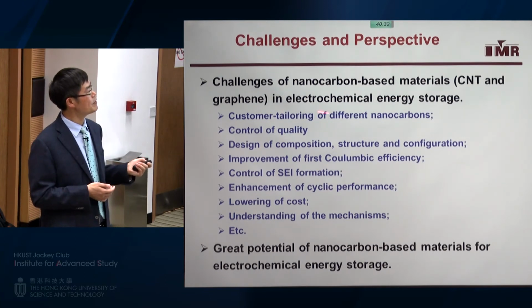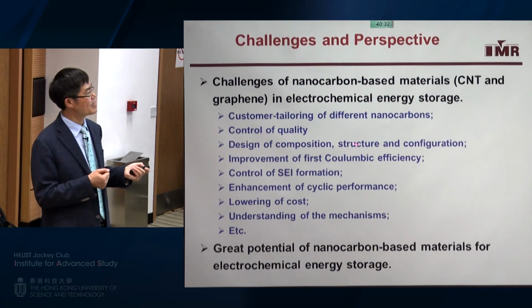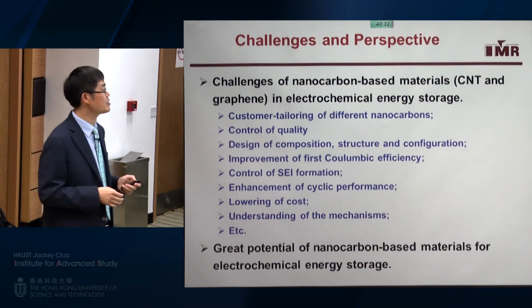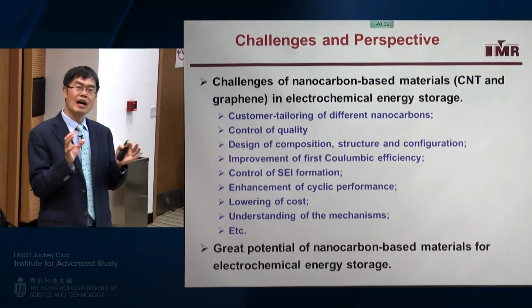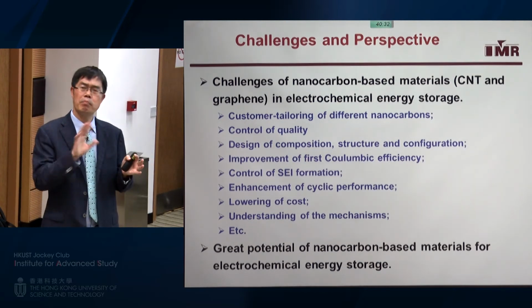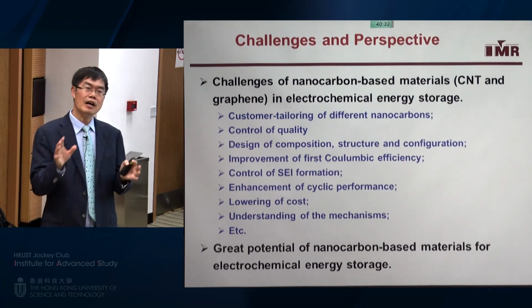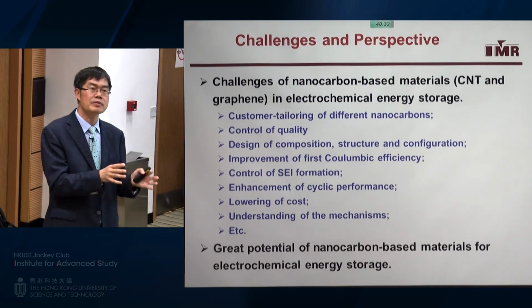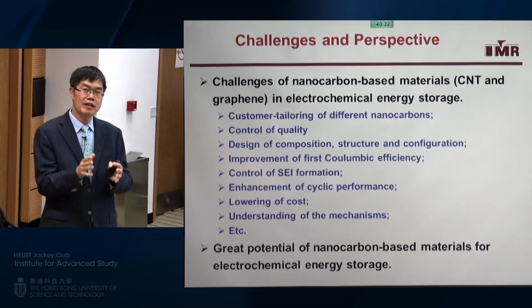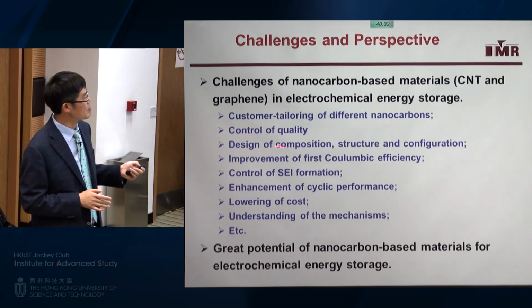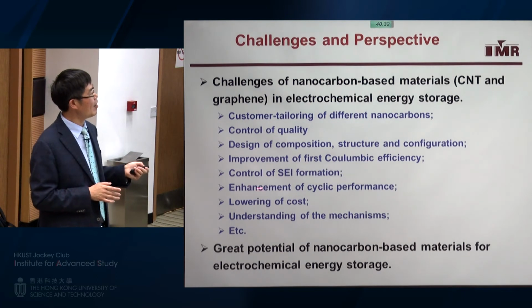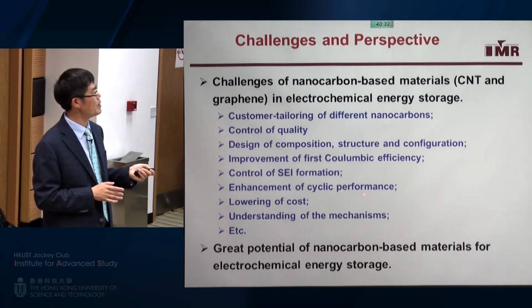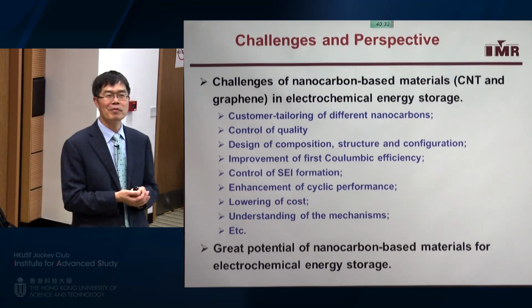We need to have tailored material with very good controllability of quality, and also we need to design the optimum composition, structure and configuration for different types of energy storage devices. Because we are using nanocarbon, basically we have poor first Coulombic efficiency. However, if we want practical use in batteries or supercapacitors, the first Coulombic efficiency is very important. So we need to improve this performance, and also the cycling performance. Of course, another problem is the cost.